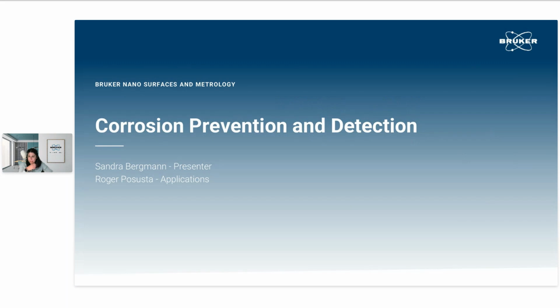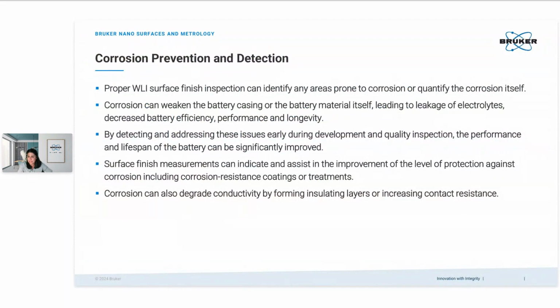A further key topic in EV is also corrosion prevention and its detection. Corrosion itself can weaken the battery casing and of course the battery material itself, which can then lead to leakage of electrolytes, decreased battery efficiency, and it can also shorten the performance and the lifetime of it. Furthermore, corrosion can also degrade the conductivity and can form insulating layers, which also increases the resistance of any contact.